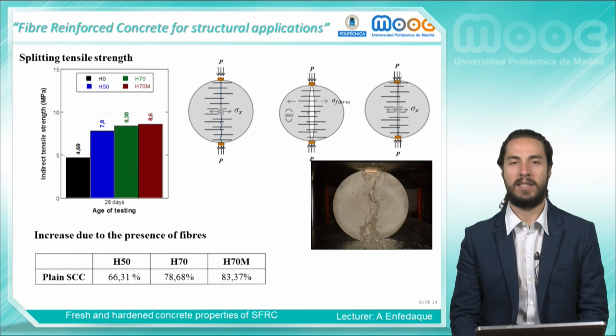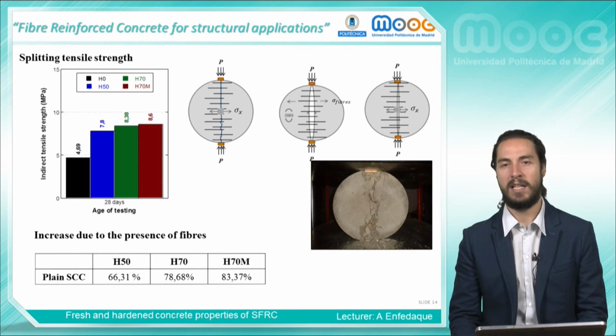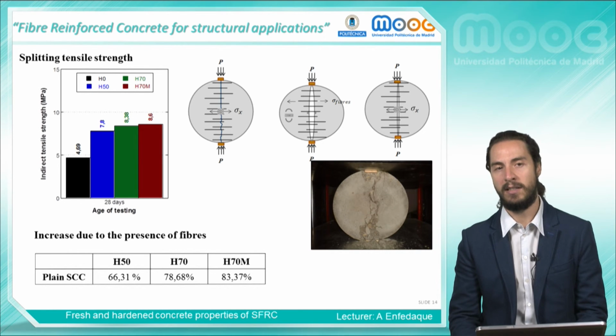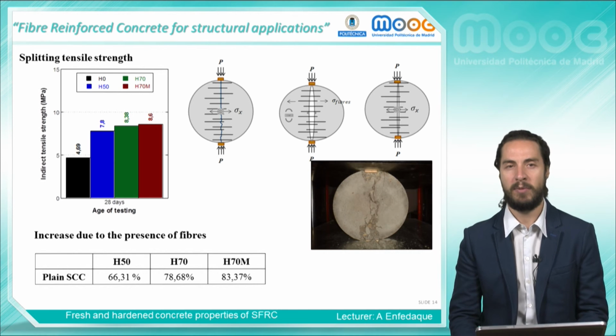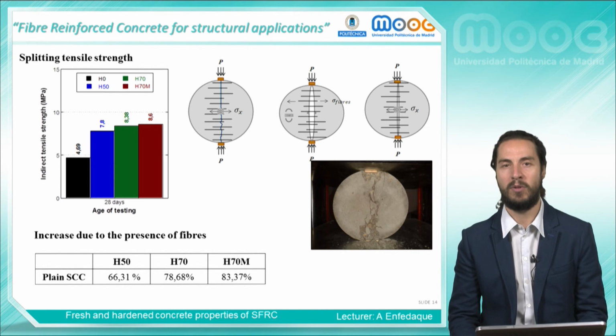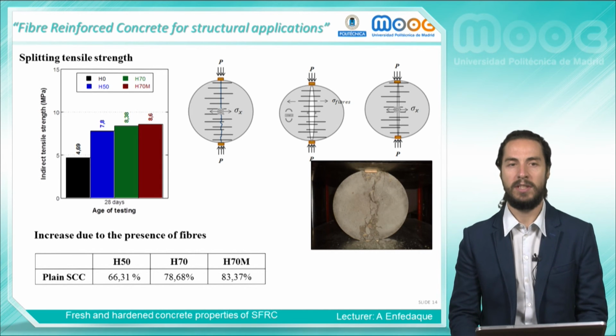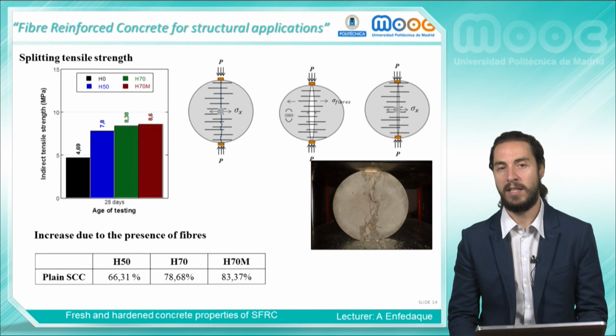In the case of the tensile splitting strength, the figure in the slide shows that the presence of fibers raised the indirect tensile strength. For the high fiber content concrete, the increase might reach up to 80% compared with the plain concrete. This indirect splitting test might provide such improvements and also show the different mode of failure. Nevertheless, it is worth noting that it is not the appropriate test for fiber reinforced concrete. Second-order effects occur during the test in fiber reinforced concrete, and thus no clear conclusions can be deduced.